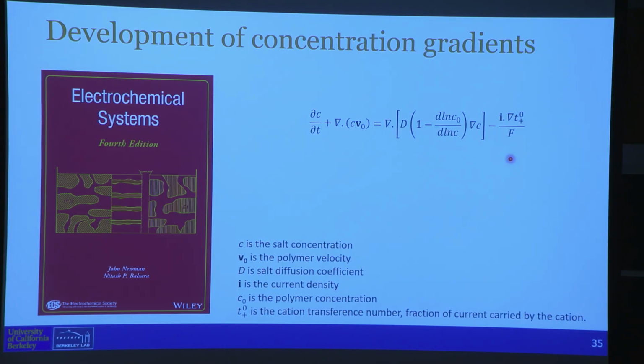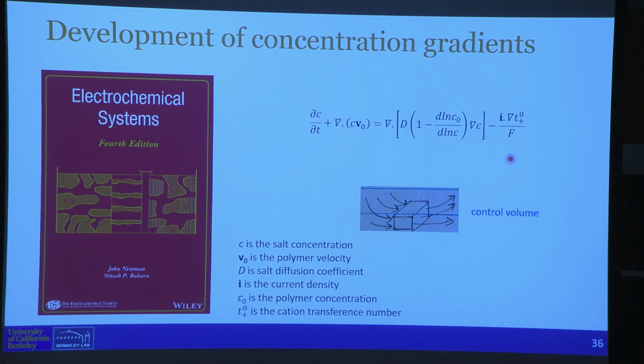But I want to tell you whether this equation for chemical engineers at least is not that scary. It really talks about a control volume and what goes in and out of your control volume. The first point is that there's an accumulation term. So if there's an imbalance, then the concentration in that control volume must go up. The second term tells you the salt that is carried by the solvent, C times V0. The third part has to do with diffusion, just ordinary diffusion. Put an ink drop in water and watch it go away. That's the law, you would say. And the final is pure Newman. It's how the current interplays with this concentration field in the form of this dot product of I times the grad of T plus 0.